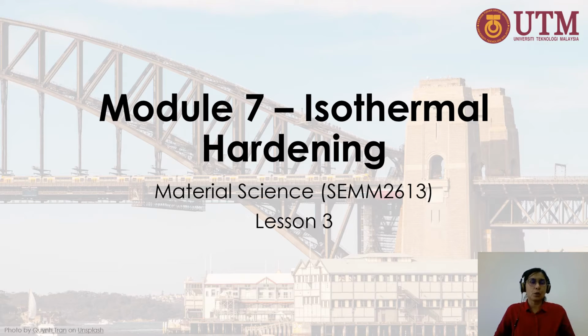In a previous video, we talked about heat treatment processes such as full annealing and normalizing, where we heat up materials, steel materials, for example, eutectoid steel. So eutectoid steel consists of 0.8% of carbon. During full annealing and normalizing, what we did is we heat it up to a certain temperature above its transformation line from austenite to pearlite or austenite to cementite. We heat it up to transform all the microstructure back to austenite.